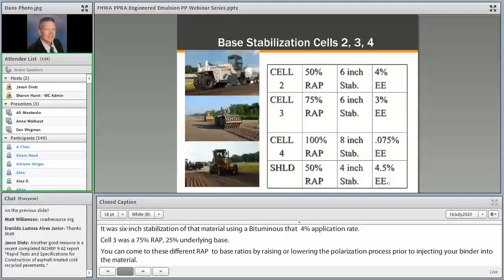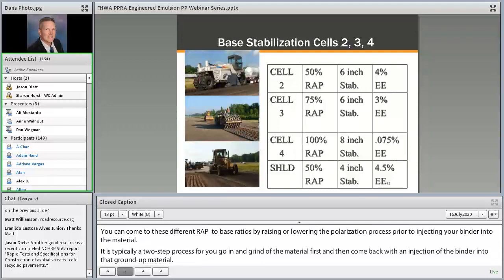And so cell 3 went to a 75% RAP, 25% base. It was also stabilized at 6 inches, but reduced the emulsion added to 3% because of the higher RAP content.